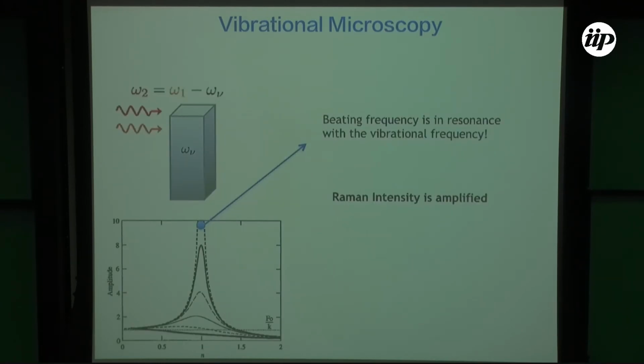But then if I put two lasers on my sample in such a way that the second laser, omega 2, has an energy that's omega 1 minus the vibrational frequency of your material, okay? So when these two lasers go into your sample, it's going to create a beating frequency that has exactly the frequency of your oscillator in your material, okay? So basically, this beating frequency is in resonance with the vibrational frequency. So we are going to create a coherent vibrational state in your material, okay? So basically the Raman intensity is going to be amplified, okay?